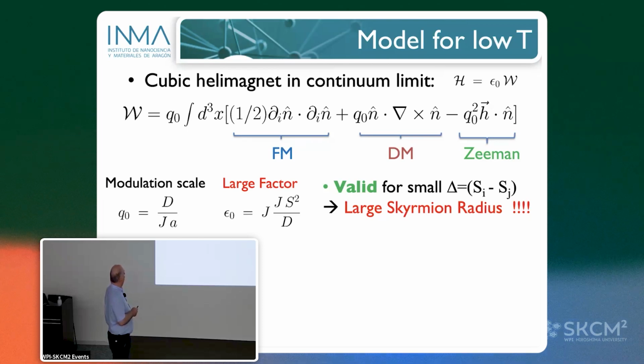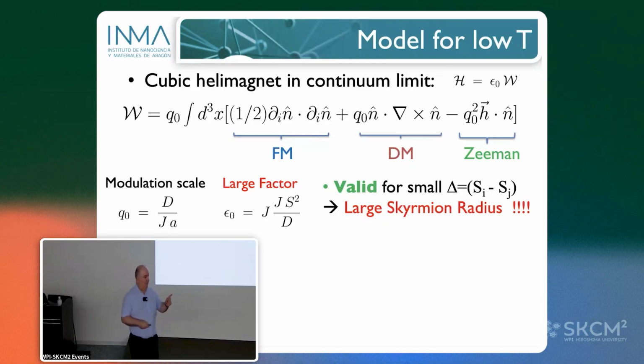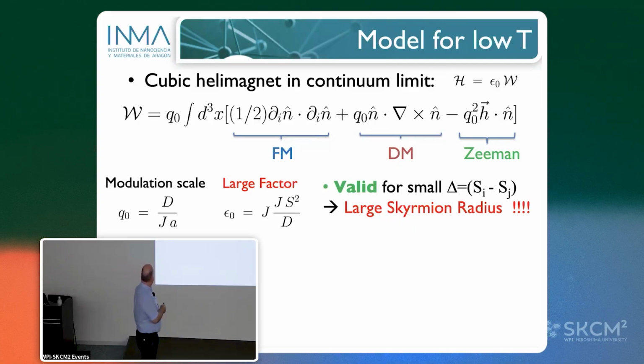Then this gradient term is coming from the ferromagnetic, from the Heisenberg interaction, and the Dzyaloshinskii-Moriya term produces this term here. Here we didn't put anisotropy, and this is the Zeeman term. N hat means a configuration of the spin with modulus 1. The spin and everything is included here in the energy. Then everyone is doing like this. Everyone is considering a density of energy like this with a classical field, N hat, which is basically the magnetization, modulus 1. With this, we have this Q, which is related with the periodicity, and the energy also related with Q and the spin.